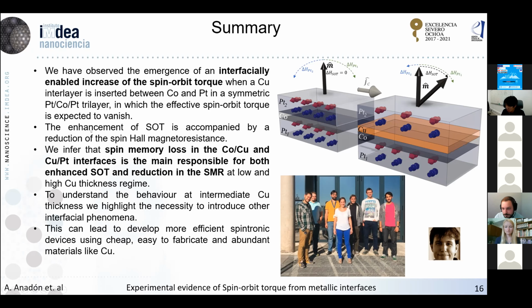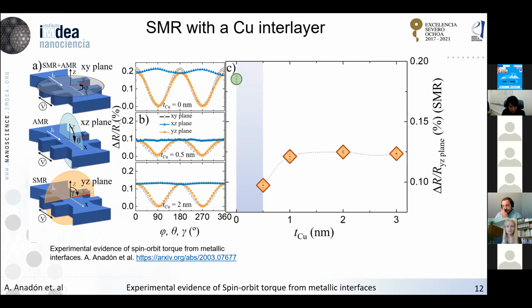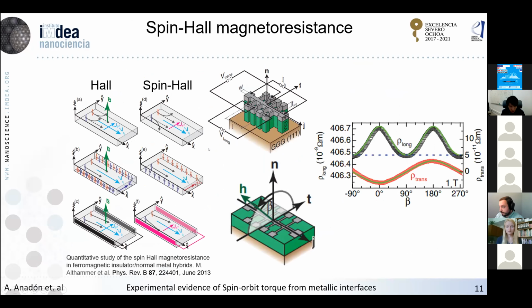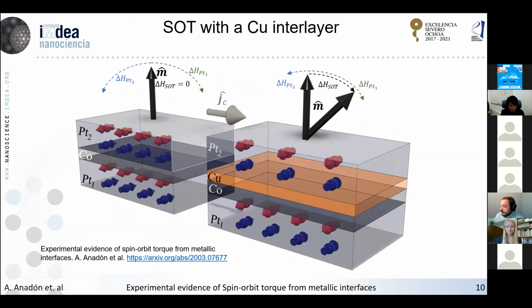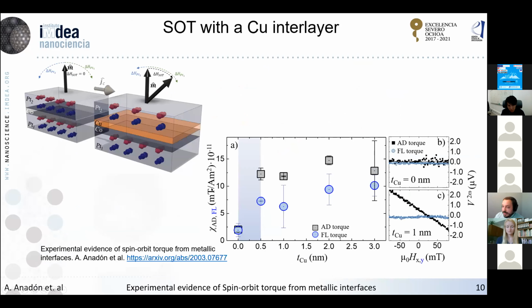So when you make these kinds of measurements, are artifacts such as Ørsted fields and things like that important to take into account? You mean the spin-orbit torque? Yeah. You basically have to consider all the artifacts, and there's already a lot of literature about it. So basically, we have subtracted the possible artifacts from the planar Hall effect and so on when you do these measurements.